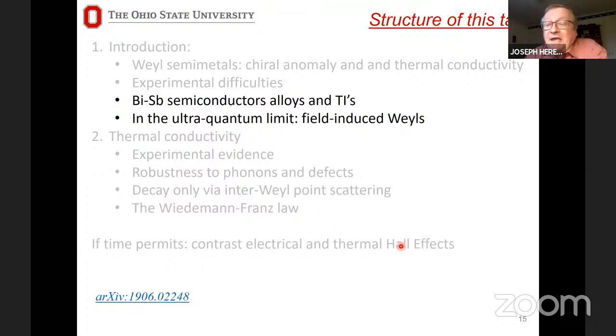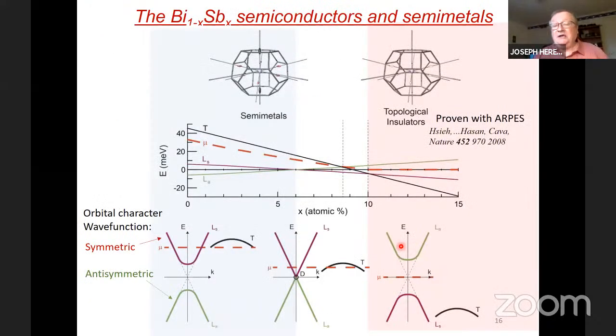All right, the next part of my talk, I need to introduce the material system, which assuming that you're not terribly familiar with it, is the bismuth antimony semiconducting system. So we all know since the 1960s that bismuth is a conventional semimetal. It has electron pockets at the L points of the Brillouin zone. It has holes at the T points of the Brillouin zone. If we look at the dispersion, there is an electron band here and a hole band here, and there is an overlap, so there are as many holes as there are electrons.